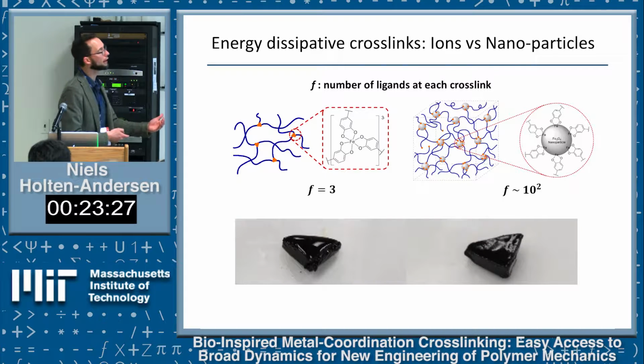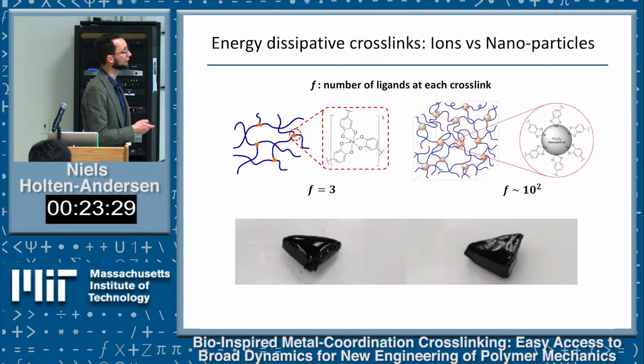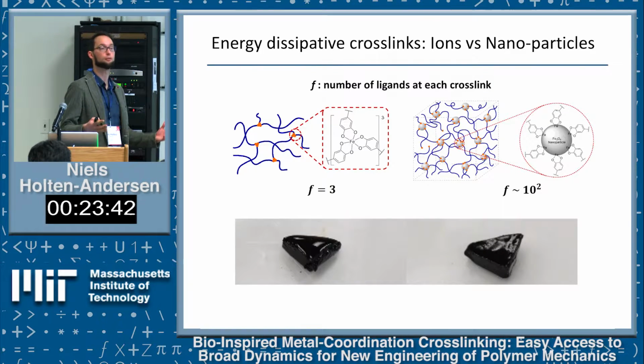So what we're trying to understand and control is a function of how many organic ligands we have bound per cross-linking species. In this case, it's only 3 for an iron ion. For the nanoparticles, depending on the size of the particles, you can get up to hundreds of ligands stuck per particle. So just by controlling the number of ligands bound per crosslink structure, you can really engineer how fluid or solid-like you want your material to be.